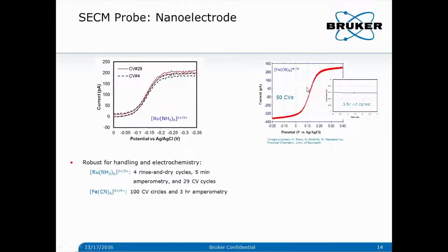And here's another example, the EC performance test in a ferrocyanide solution. As you can see, this is actually 50 continuous CV cycles plotted together, and you will see no difference at all among these CV cycles. Indeed, before these CV scans, the sample had been tested for 3 hours of amperometric measurement. As shown here, there's no performance drop observed at all.